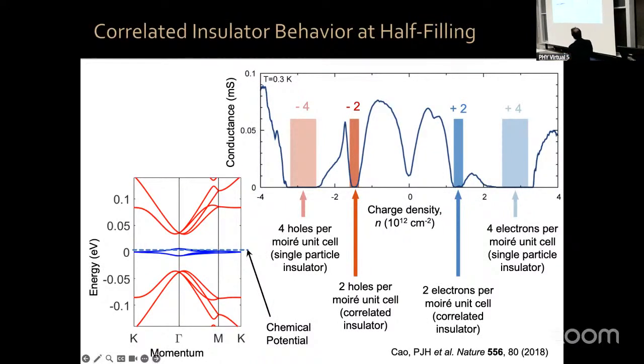Now, the other thing we saw: these measurements were 2-terminal measurements, which means the following. I have a source and a drain, apply a voltage, and measure a current. This is a geometry convenient to use if you're looking for insulators, and we were in fact looking for insulators. Because if you have a series resistance from your contacts or other stuff, it doesn't matter, since you expect to measure infinite resistance anyway. Who cares if there's an additional extra resistance?